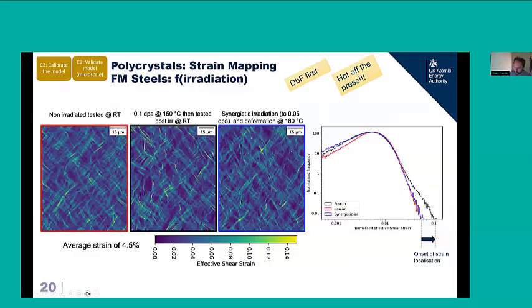And then this is some example data from that experiment or additional experiments. So we've got grade 91 steel on the far left, and then the strain heterogeneity after irradiation to 0.1 dpa. So this is what we call cook and look. We've irradiated to a certain dose. It doesn't matter about the units of that dose. And when we've tested the material, it's showing that sort of localization but it's a bit more robust compared to the Zirc alloy 4. And then looking at what happens when we deform the material under irradiation, which is far more representative of the fusion environment and all nuclear environments that are of interest to us, and showing the slightly different effects that can have. So this is really quite early work to develop information for our models, but it's yielding some interesting results already.